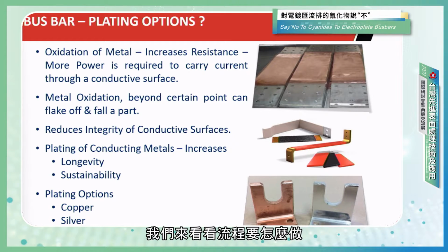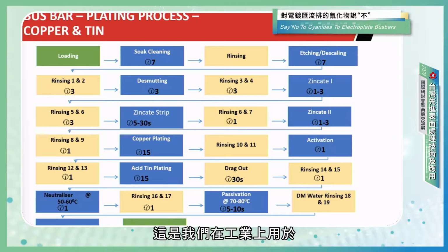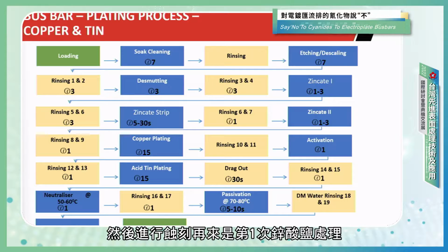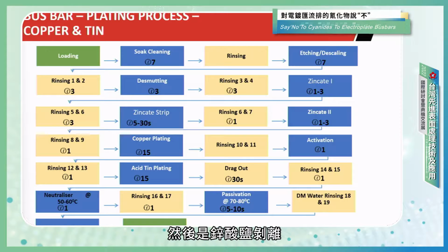Let's see about the processes. You can see some photographs of the plated components, and this is the normal process sequence industry uses for plating busbars while doing copper-tin plating. It starts with specialized soak cleaning, so that it doesn't age the base aluminum material. Then etching, zincate 1, desmutting, zinc strip, zincate 2, strike copper coating, tin plating, and then neutralization, passivation, and drying.